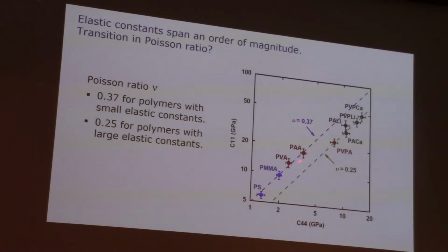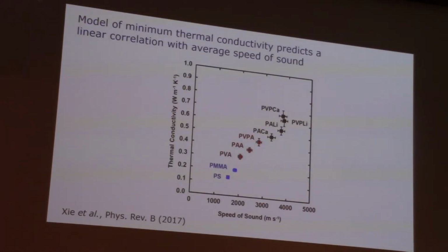And these are the measured values for all these different films, going from van der Waals bonded polystyrene to ionically bonded, this ionic salt, polymer salt material. And it spans almost a factor of 10 or so in elastic constants. So we can vary the elastic constants of the polymer by about a factor of 10.